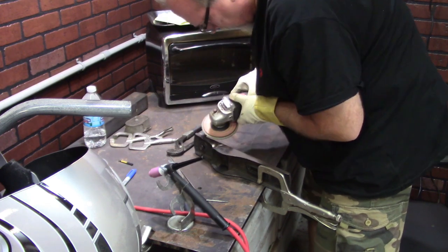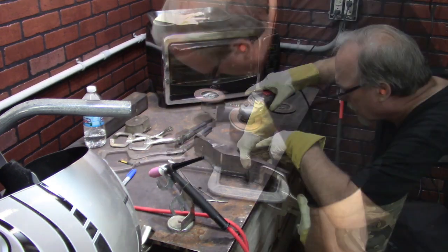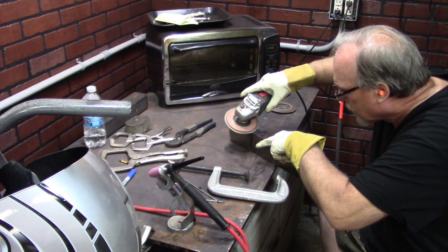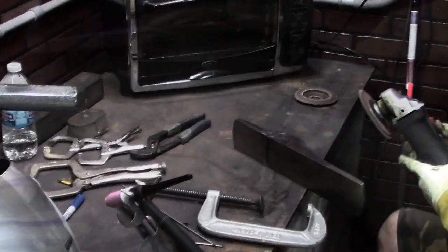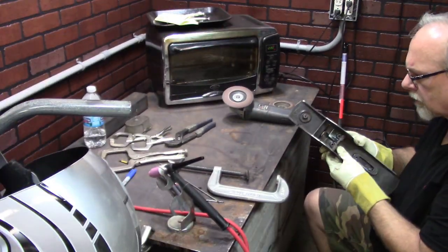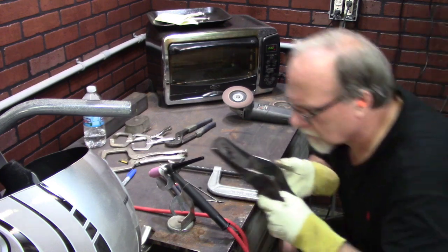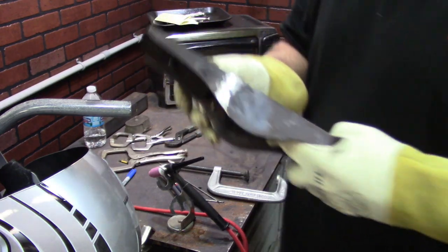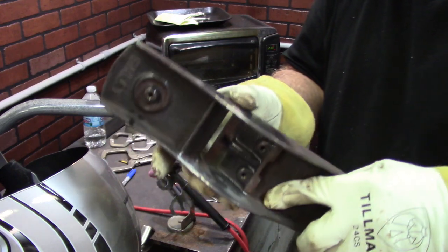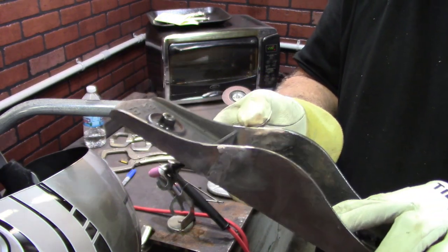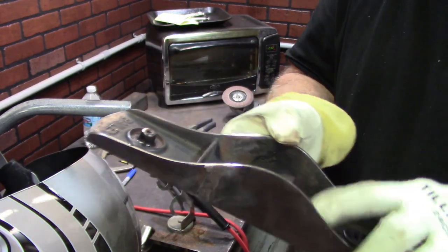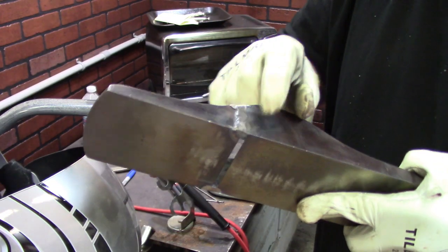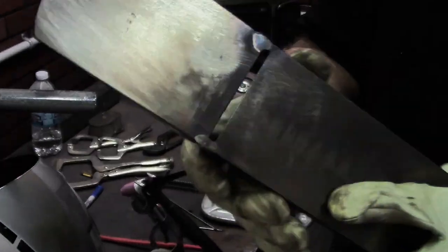This material was surprisingly difficult to grind away. The cast iron is actually, I believe, softer than the material I was grinding on. So it was kind of tricky. There's a couple places I had gouged into the cast iron, and I had to go back and fill those up. That's a pretty good indication.